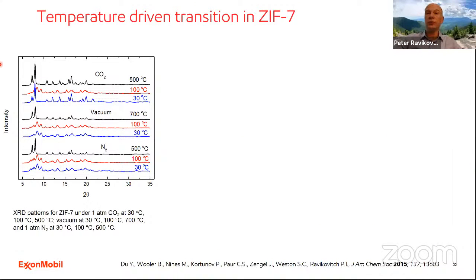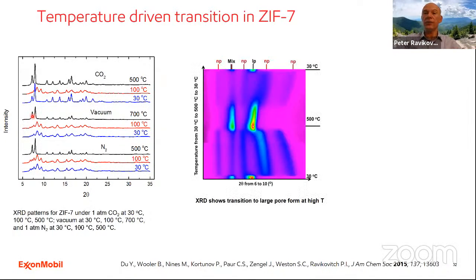So if you put this material in an XRD cell and you start, let's say, in vacuum at room temperature, the material is in the narrow pore phase. And as you heat it up to high temperature, it actually transitions to the large symmetrical, hexagonal pore phase. This is another look at this, where you do the heating and it transitions to the large pore phase, but then upon cooling, it actually reverses back to the narrow pore phase. So it is an equilibrium transition.